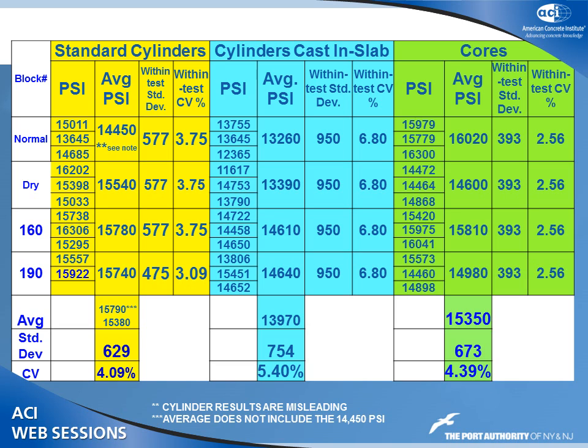Here's again the same concrete, where we tried to get the temperature of the concrete up to 160 degrees in 24 hours, what we could, and they got up there in about 2 days. And here's what we got out of the cylinders, and those cylinders were also put in that same bath where we tried to get this elevated temperature. Same with this block, and the cores, which we took out in 56 days. Once we did this with this temperature for 2 days, then we cured it in the moisture. All of this was cured in the moisture for 56 days. These are all 56-day breaks.